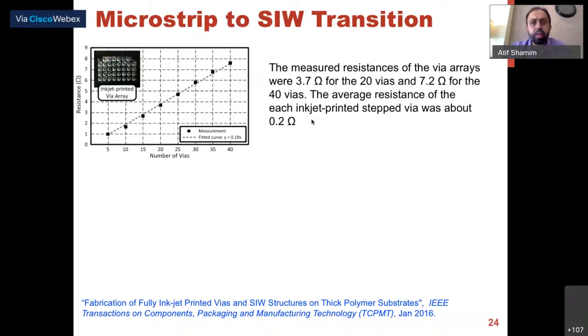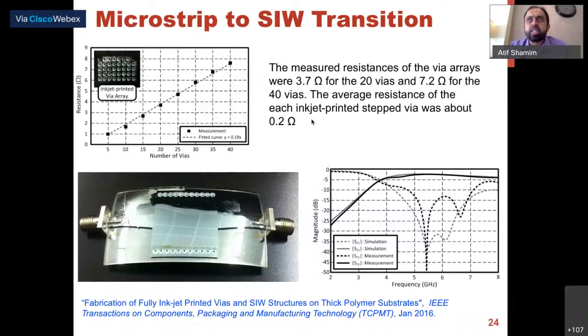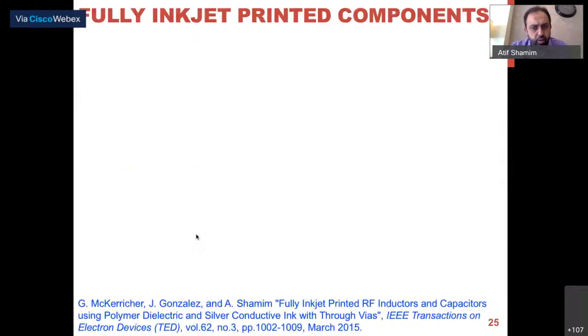Now I've just shown you so far the printing of metallic ink, so on conventional and unconventional substrate, but the idea of printing everything means that we also want to print the substrates, we also want to print the dielectrics, and for that matter we developed an organic ink, PVP ink as a dielectric, and we created a multi-layer process. You could see at the bottom here, so you could have a metal layer, and then you could have dielectric layers, and there's an interesting via here as well, and then you have another dielectric layer.